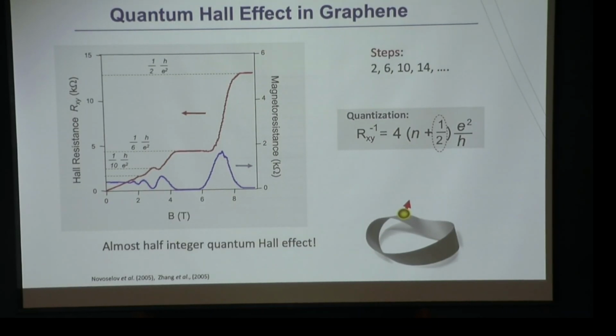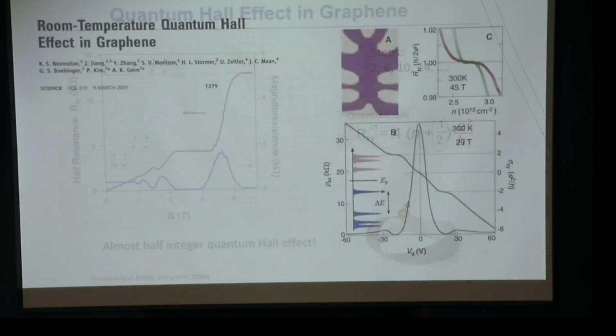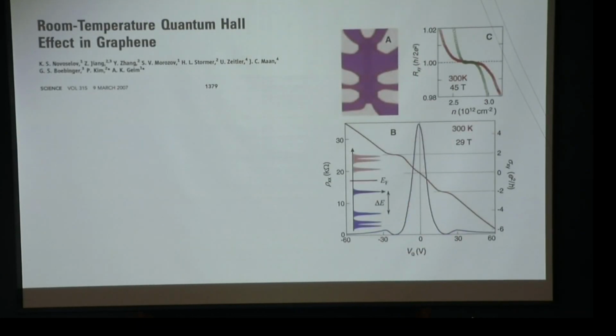Of course, that is the phase associated with the linear dispersion. Once you apply the magnetic field, the Landau levels appear, but the Landau level separation is very different, especially the first Landau level separation between the zeroth level and the first one, which is big because of this linear dispersion relation. This means that with a decent magnetic field, say 30 Tesla or 40 Tesla, the gap becomes several thousand Kelvin, which means that the quantum effect appears at room temperature. Right, so not superconductivity, but it is working with the quantum effect at room temperature.